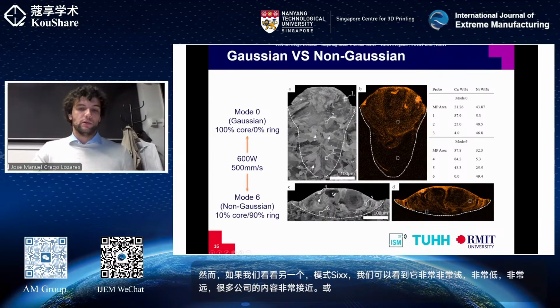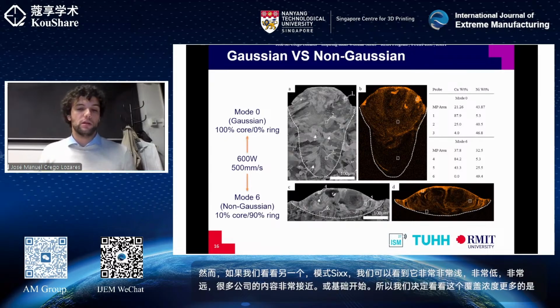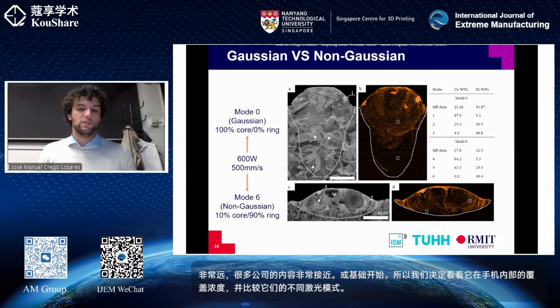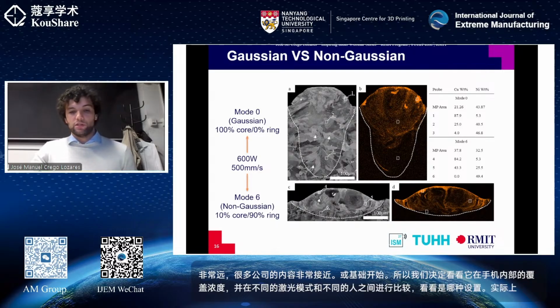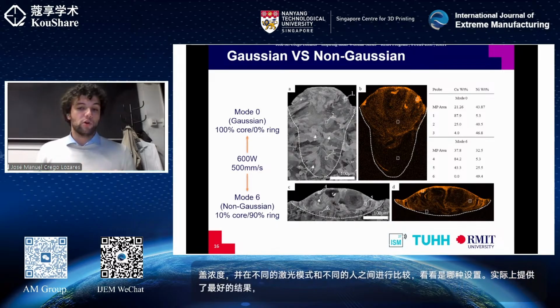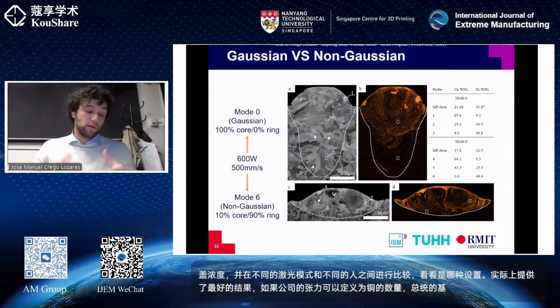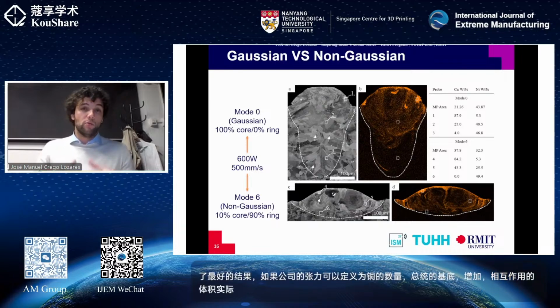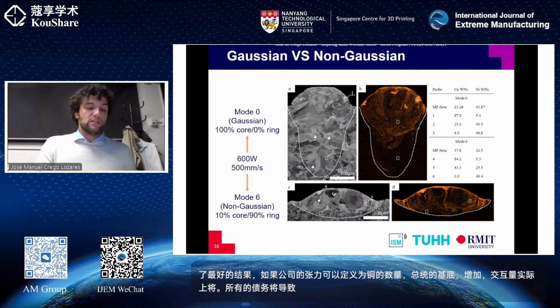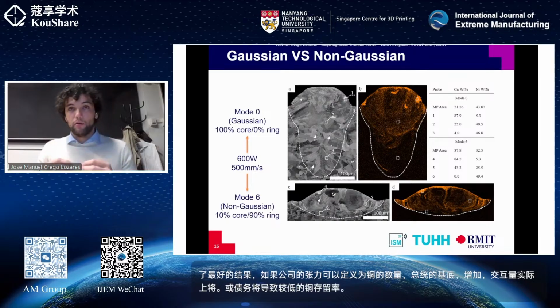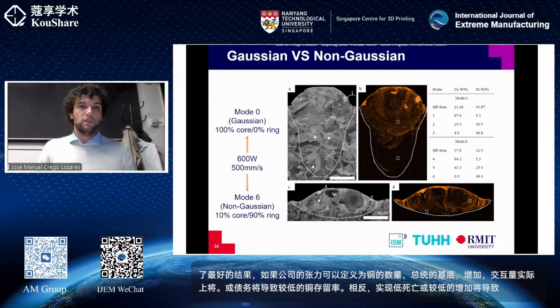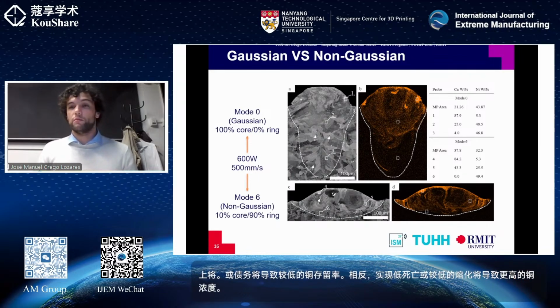So we decided to take a look at this copper concentration a bit more inside the melt pool and compare them for different laser modes and for different processing parameters to see which setup actually provided the best results. If copper retention can be defined as the amount of copper present on top of the substrate, increasing the interaction volume, or the depth, will lead to a lower copper retention. On the contrary, achieving low depth or lower remelting will lead to a higher concentration of copper. And this is what we are seeing with mode 6.